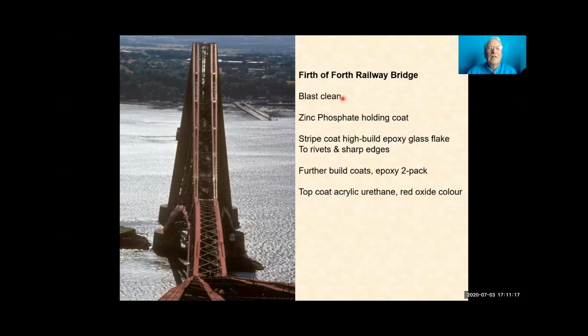Obviously, this is all right out over the sea here, so they had to put something on immediately so that it didn't rust. And it was zinc phosphate, so zinc because of the cathodic protection. Then stripe coat, that means the edges and all the difficult bits and the rivets were coated with a high build epoxy glass flakes to actually build up the vulnerable areas. Then the 2 further build coats of that epoxy were put on.